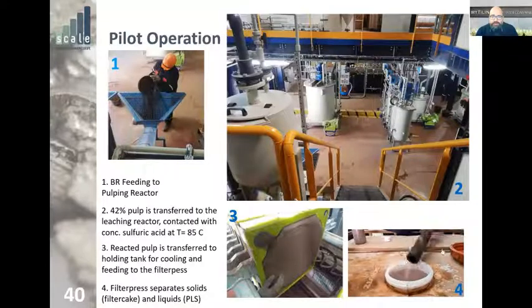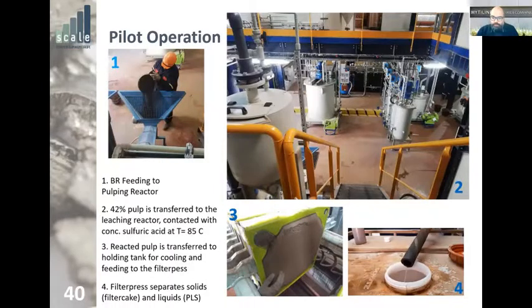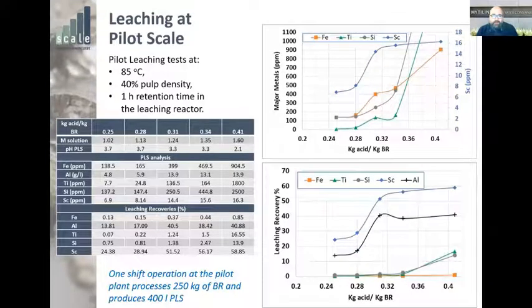It was very essential for us. Here also you can see the first time we saw a clear liquid solution coming out of our filter press. It was very important for us to translate the process into an industrially viable process. So instead of this 2-cycle, we discovered that we can get equivalent results if we double the pulp density, something that we can do in a pilot, not so easy in a lab scale. So we work at 40% pulp density, 1 hour retention time, and even did a small experimental test with different acid to bauxite residue ratios inside the pilot.